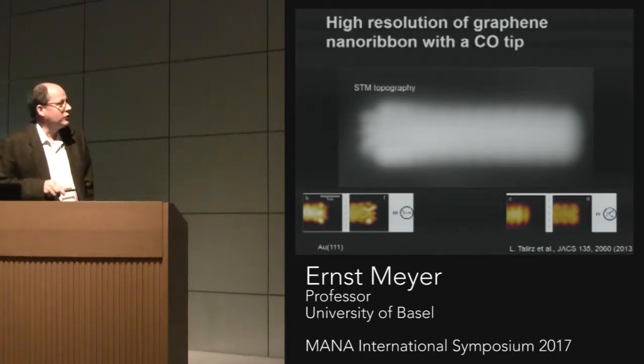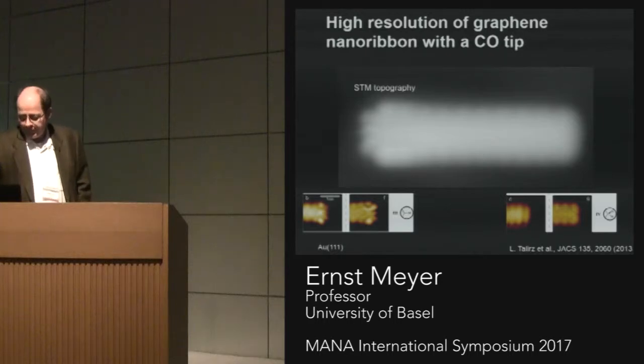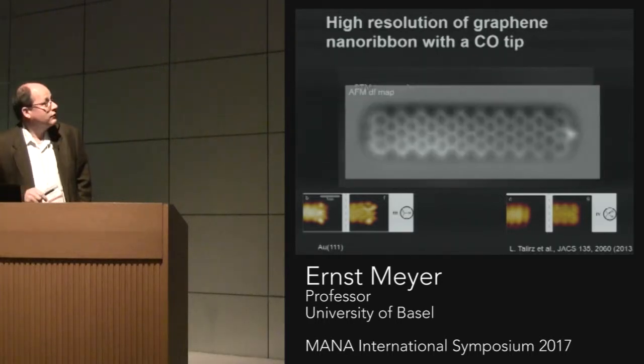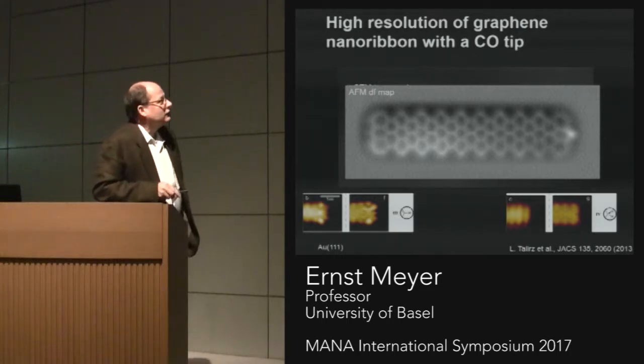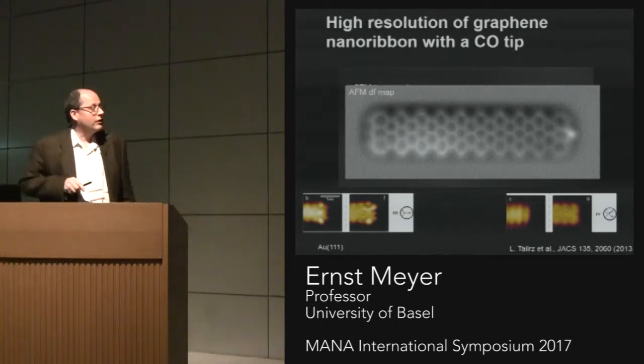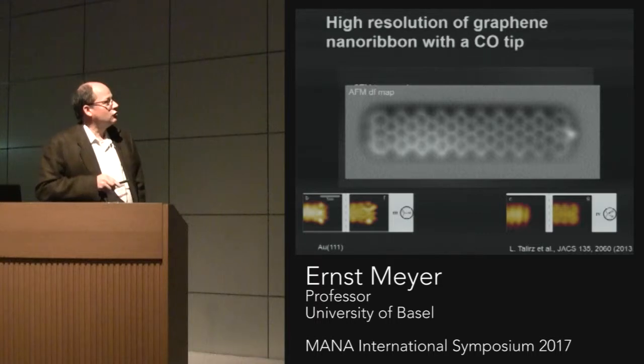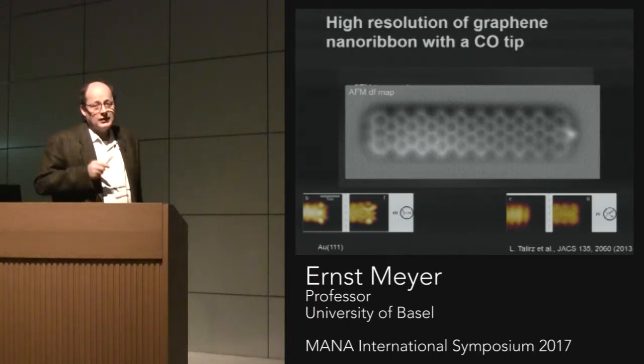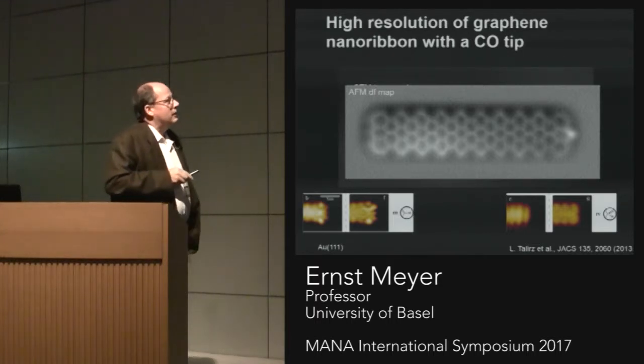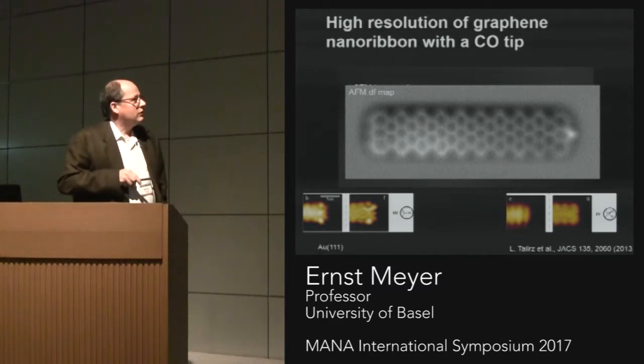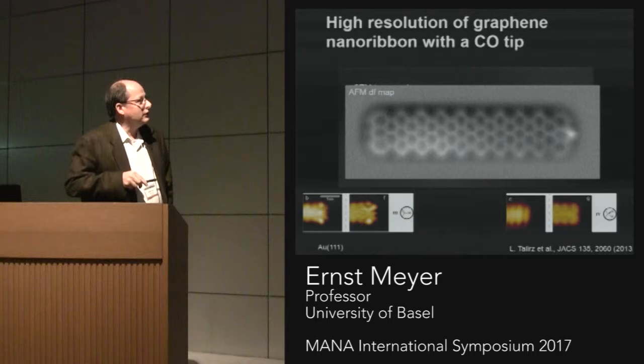So this is an example of an STM picture of such a ribbon. And now I show you how it looks in AFM. So I always call that sort of a Hubble effect. So you see that you really get a very improvement in the resolution, because the CO that's now attached to the tip, for the imaging here, you can get closer to the surface, and now you really can see all the details of this ribbon.